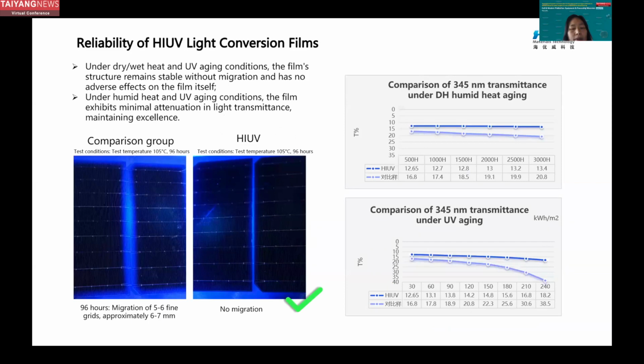Here is the reliability test of our conversion film. The conversion film is only used on the front side. For the cell and cell gap part, the conversion film, with the external environment such as dry, humid, heat, and UV irradiation, is actually migrating downward. But this part of our film, no matter under what situation, with what temperature, what UV, including ultra UV, does not migrate. That is to say, through the performance of this test, our structure is different from others.